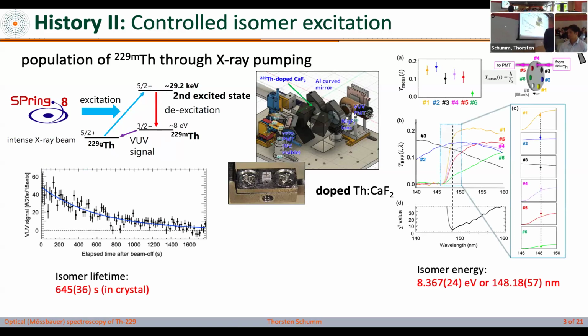And then the Japanese group, before the photomultiplier, put a set of filter wheels, and by changing the filter wheels they were able to determine also the wavelength, and that fits quite nicely to the energy that was predicted in the CERN experiment. So these two experiments all go through higher states. They don't start in the ground state and go to the first excited state.